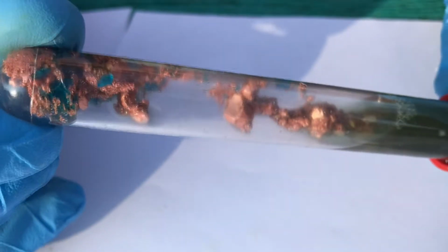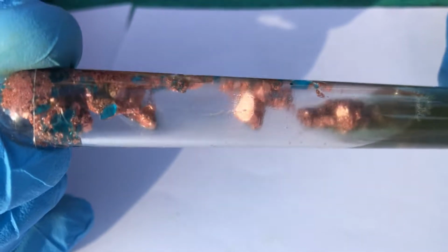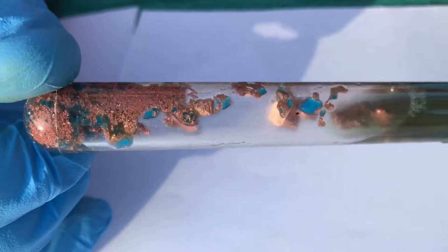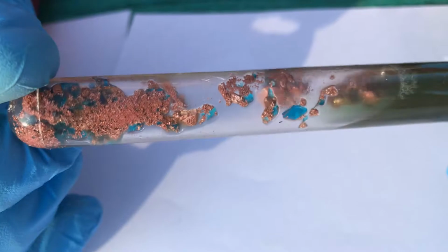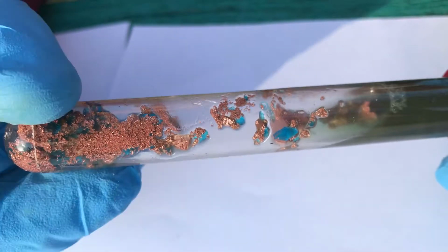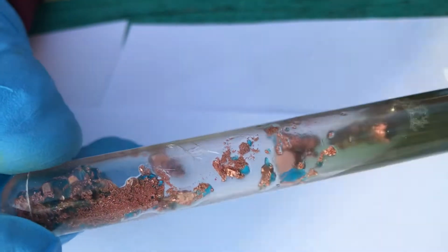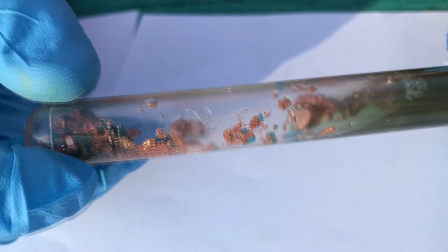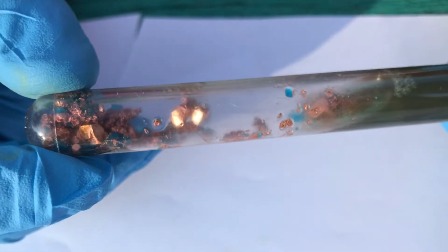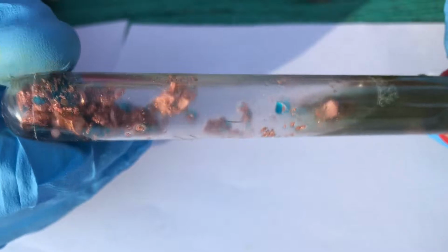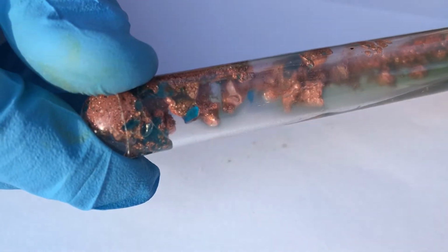Interestingly enough, the copper reacted with the sulfuric acid and the oxygen gas that was in the tube and formed copper sulfate. The formed solution was supersaturated, so it precipitated out some copper sulfate crystals. In the test tube, you can see the pure copper powder as well as some large crystals of the metal.